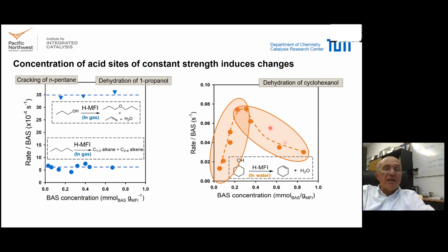On the one side, this decrease is related to an inability of more reactant molecules to be adsorbed in the pores as the hydronium ion concentration increases. But beyond that, we will also show on a later slide that it is about the symmetry, about a minimum in the distance between two hydronium ions that is optimum for such a reaction rate.